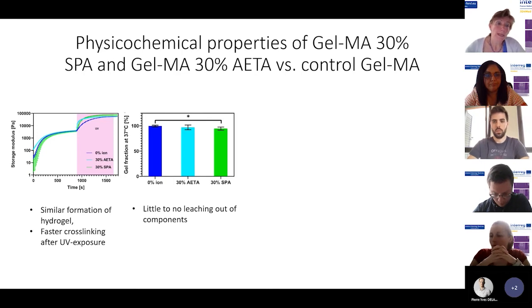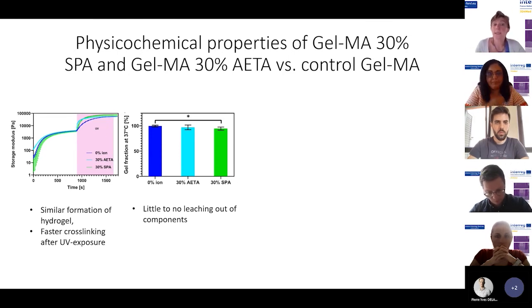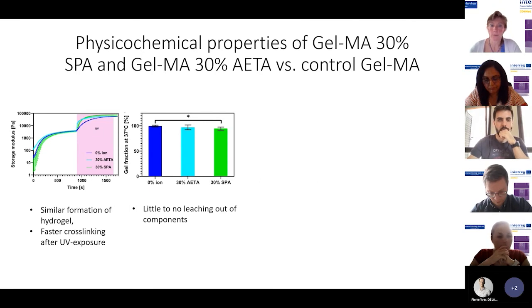And then we also looked at the gel fraction when incubating at 37 degrees. Why do we do this? To see whether there would be, for example, a degradation happening inside the polymer, so that maybe toxic components are leaching out of the hydrogel. But luckily, there was not a big change in the gel fraction at 37 degrees Celsius. There is a small difference in the SPA gel, but as you can see, it's still small compared to the control GelMA condition. So this allows us to believe that there will not be a large toxicity of these hydrogels due to the leakage of monomers or other components.